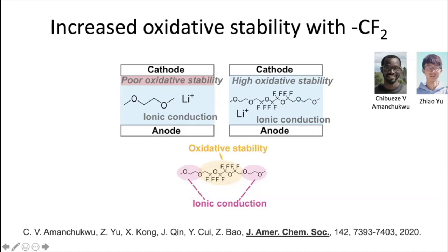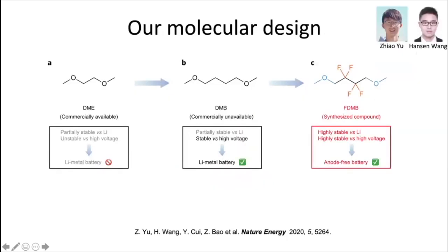Here we found that as we systematically change the number of CF2 groups incorporated, we change the oxidative potential of this molecule. And the electron withdrawing effect can indeed help make the ethylene oxide more stable towards high voltage cathodes such as NMC, compared to the one without any fluoro substitution. So with this information, we started thinking about how we can design electrolyte molecules that can potentially provide both high stability at the lithium metal side as well as oxidative stability at the cathode side.